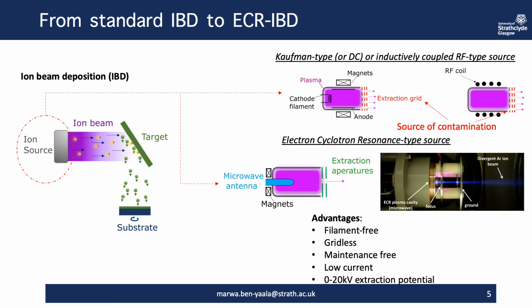So in both Kaufman and RF source, ions are extracted and then accelerated using a grid system presented here by the red dashes, and this grid presents a source of contamination for the final coatings. However, in the ECR source, the ion beam is formed by injecting the sputtering gas into a resonant microwave cavity, where it gets ionized, and the highly confined beam is then extracted through apertures.